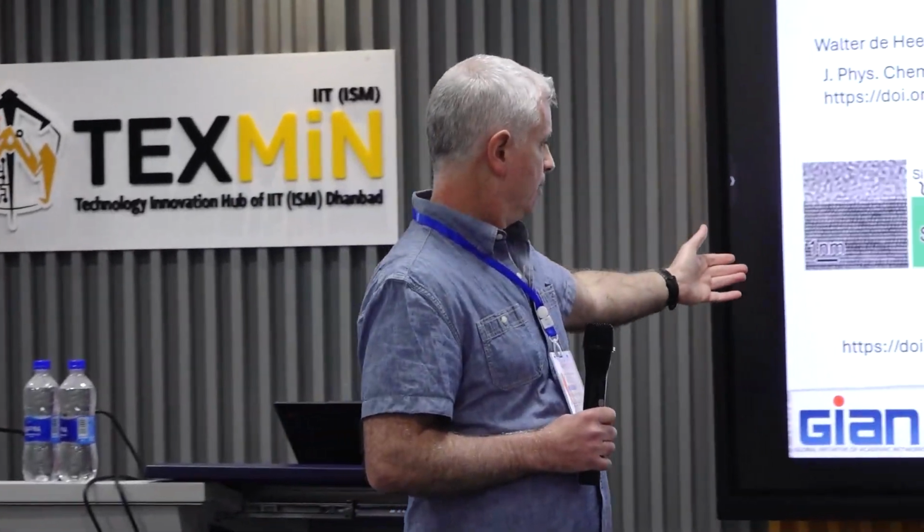What happens is that when you heat it up in vacuum, at high temperatures above 1800 degrees, close to 2000, even a bit more, the silicon selectively evaporates out, sublimates out from the silicon carbide, leaving the carbon behind. This carbon, at high temperatures, again, forms the graphitic material.